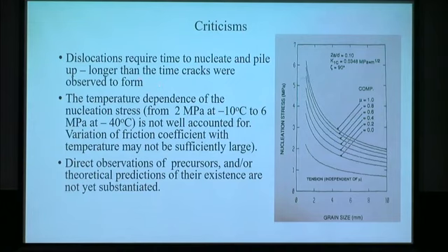The cracks that were observed to form experimentally could occur within maybe 10-20 seconds, but if you assume a dislocation pileup mechanism, maybe it would take longer than that. So there was some argument that this mechanism works only for a very slow rate of loading, in which there will be sufficient time for the dislocations to pile up.